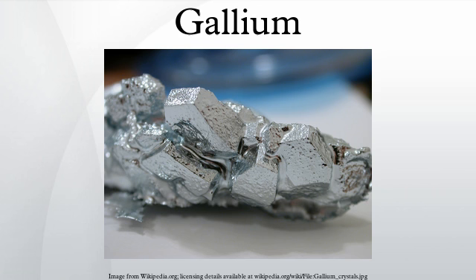Applications: the semiconductor applications dominate the commercial use of gallium, accounting for 98% of applications. Your next major application is for gadolinium gallium garnets. Semiconductors. Because of this application, extremely high purity gallium is commercially available. Gallium arsenide and gallium nitride used in electronic components represented about 98% of the gallium consumption in the United States in 2007. About 66% of semiconductor gallium is used in the U.S.